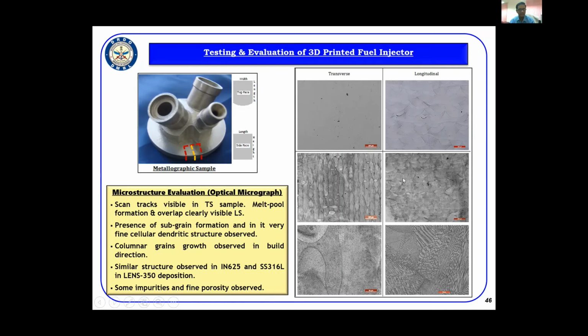And the presence of subgrain formation and very fine cellular grain structure, which is very common for 3D printed materials, has also been observed. We have also seen columnar grains growing in the build direction. In the build direction, the grains grow in a columnar manner because of the remelting of the previous layer of material. As per our earlier experience of DED metal 3D printing using the other technology, the LENS facility, a similar structure was obtained on 625 and 316 materials in LENS deposition.